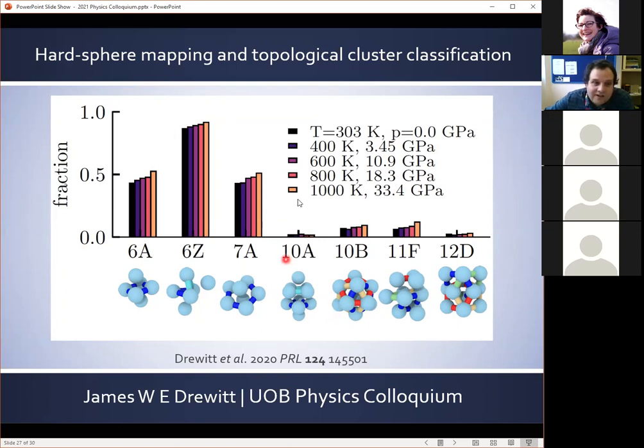from various classical simulations. And so in this plot here, if we consider the ab initio molecular dynamics simulations just above the melting curve, this figure tracks how the topological cluster classification features change from low to high pressure and temperature conditions.